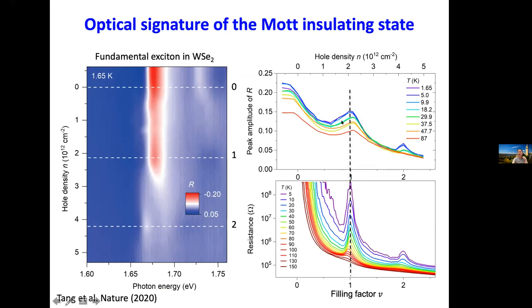And the higher absorbance is presumably due to the insulating behavior and the less screening for the electron holes. This is a contour plot when we continuously change the filling factor of this peak. If you look carefully, you might see fine features between 0 and 1.